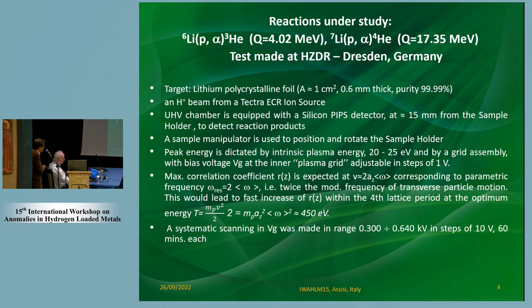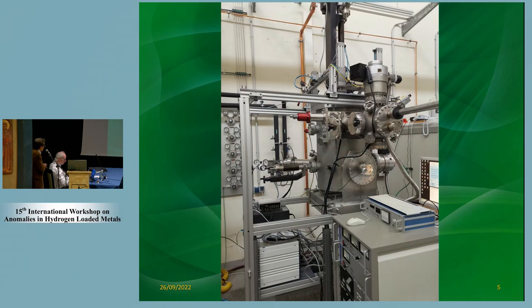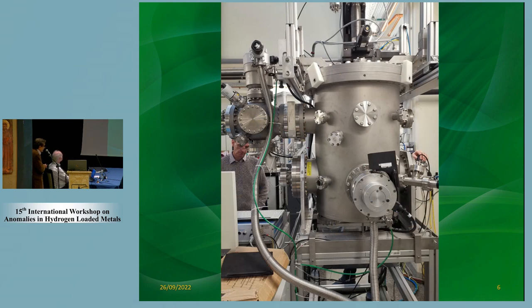So what we did is a systematic scan of this grid voltage, in the range where we could expect to observe some reaction with production of helium particles. So this is a picture of the apparatus, another picture, quite standard. You should consider that I did this test alone, only with the help of a technician from the German laboratory. By the way, this man here is the head of the ion source laboratory in Rossendorf. And I had only 2 weeks to do that. So I could not check all the various aspects, for instance to measure the calibration accurately and to get rid of the noise, etc. There was not enough time.